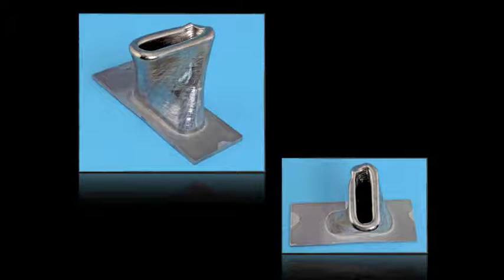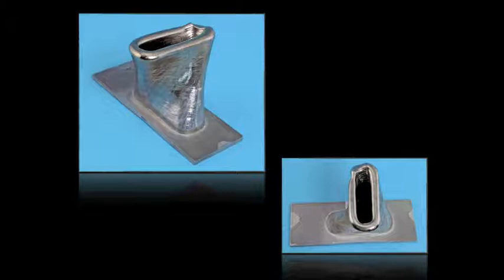This part actually has a fairly good surface finish as built but if we wanted to further refine that surface finish to smooth it out, you could either do additional machining or a secondary beam pass where you melt that surface to give you an RMS finish of about eight which is close to a mirror surface.